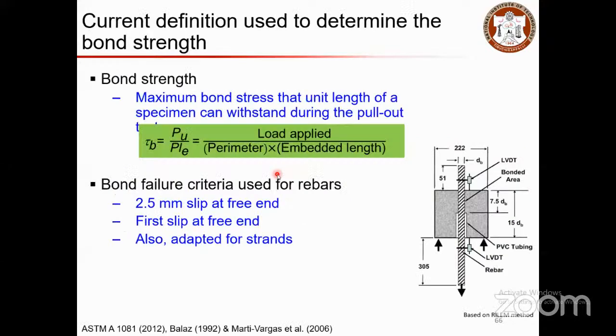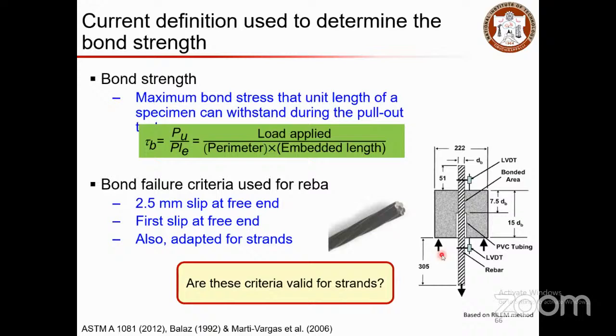For conventional strength concrete, you all know that we can determine the bond strength with a pull-out test, casting a simple cube specimen with embedded rebar, fixing one end and applying a pulling force at the other end to pull the rebar out of the concrete. The bond failure criterion used for rebars is 2.5 mm slip at the free end, measured at the free end. Or can this be adapted for the strands?